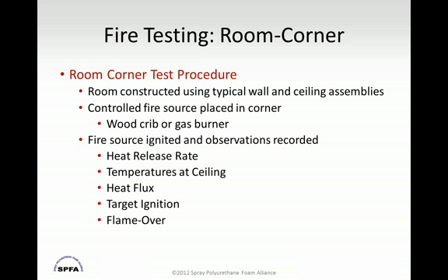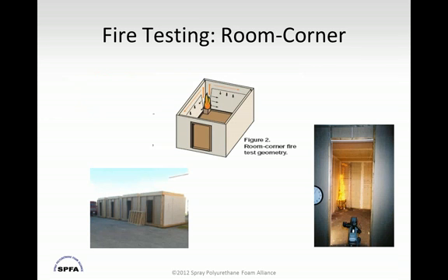And this fire source is ignited, and during a period of time, we measure certain things like heat release rate from the room, the temperatures at the ceiling of the room, and the heat flux measured at the floor of the room. Some call it the paper partition test. This is where we actually roll up newspapers and put them on the floor, and when those newspapers get hot enough, they'll ignite. And then finally, a very easy visual test, which is flashover. And again, you'll see this in the video that we have of a fire test.